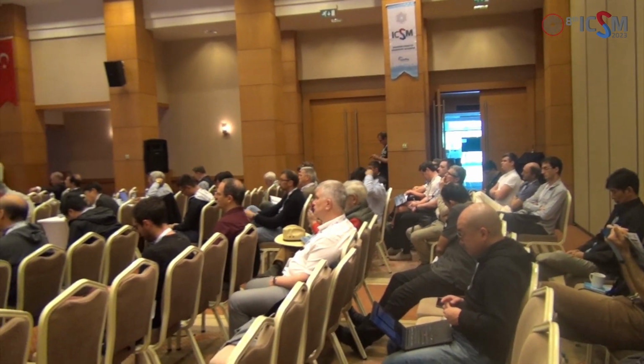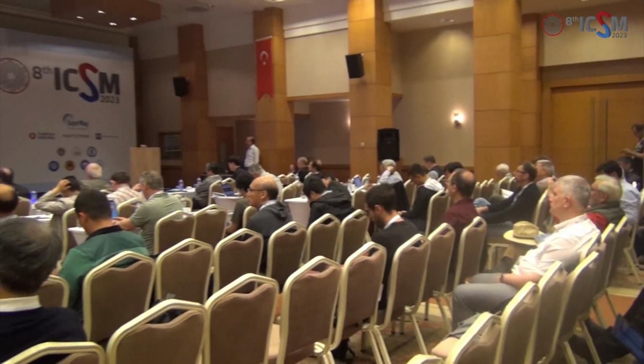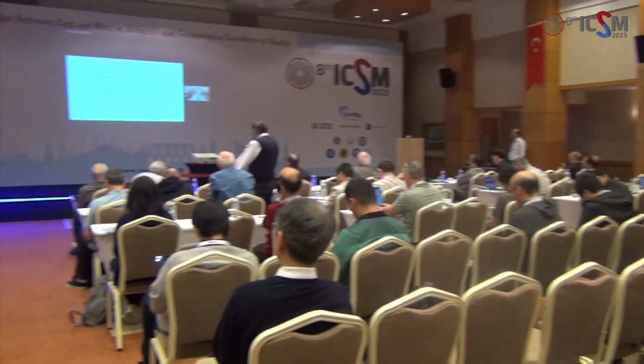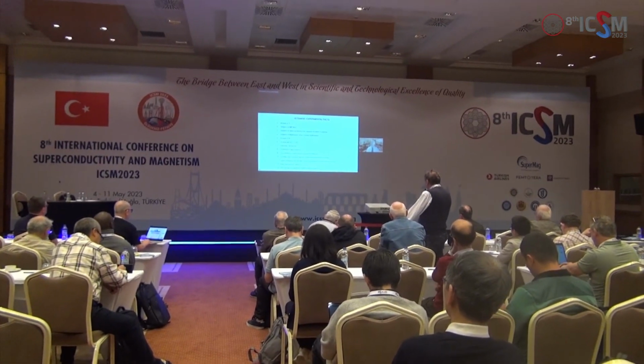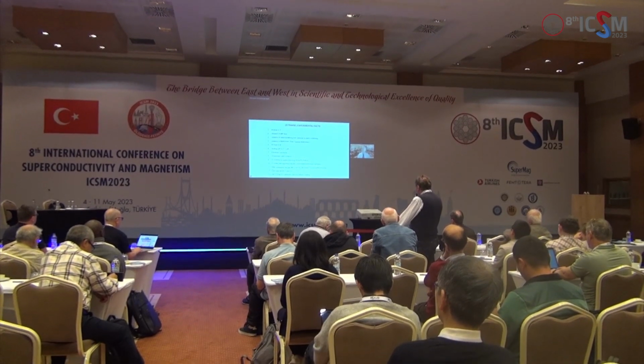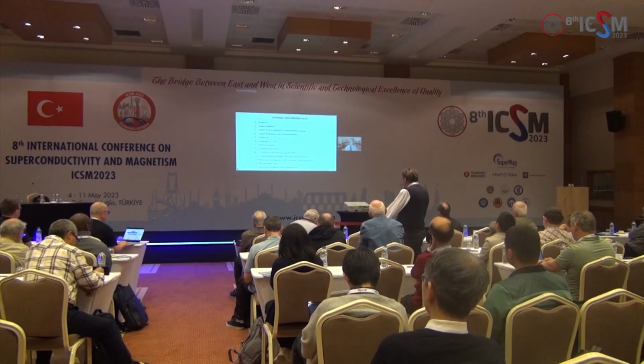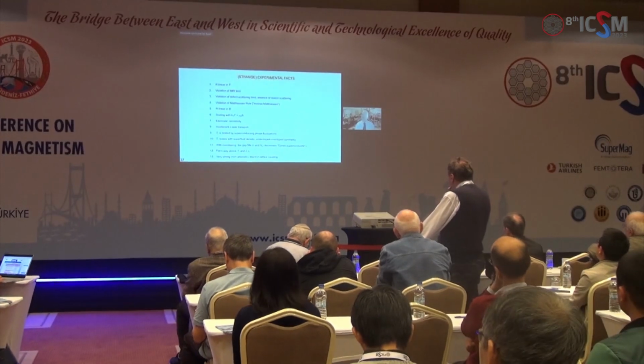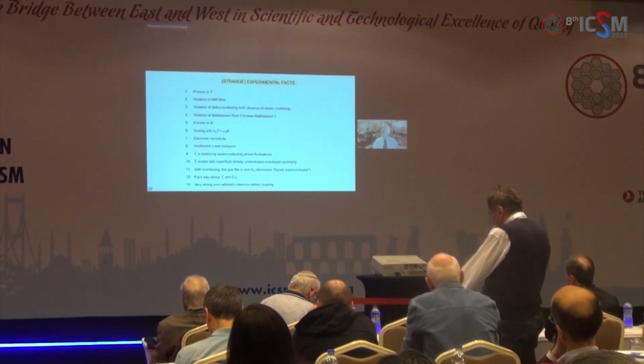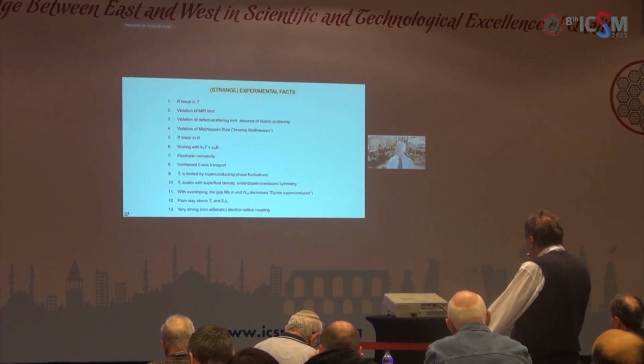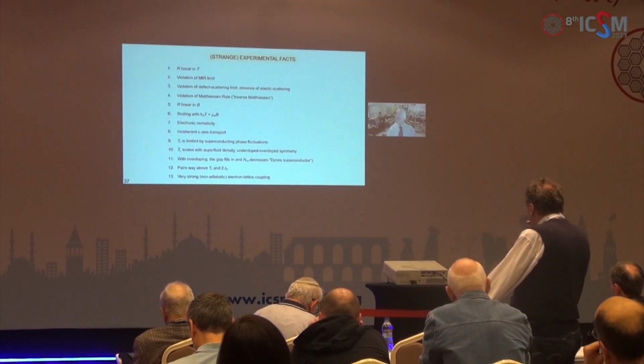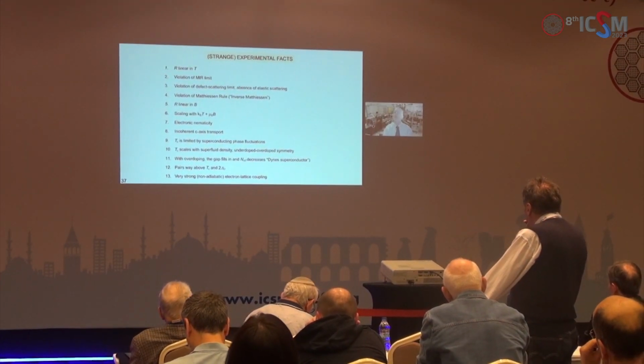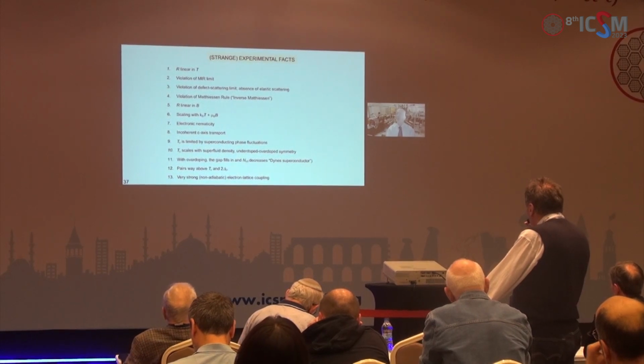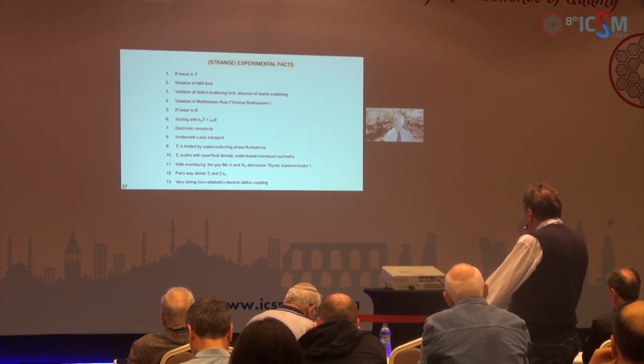And then there are 10 other examples. We also put different barriers when we make these tunnel junctions. Not only lanthanum cuprate, but we have done aluminates, zinc oxides, titanates, nickelates, cobaltates, and so on. But of course, there is a limit to what you can do. If it is really, really unstable, then it decomposes and you get secondary phase nucleations. I've seen that many times. And then, we just switch the machine off and we come tomorrow again.